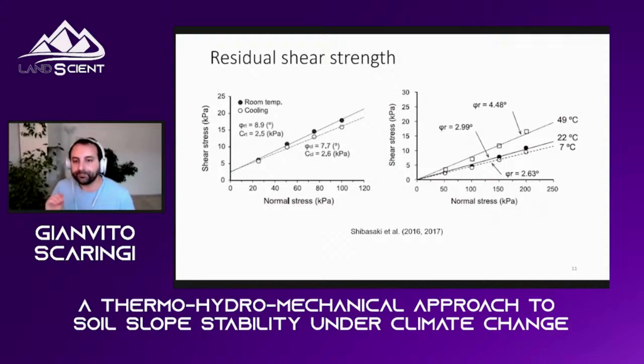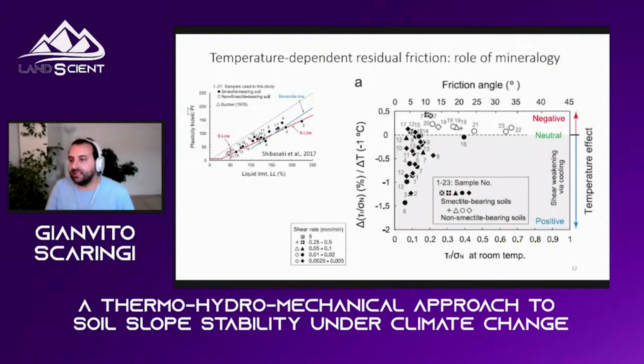However, this thermal sensitivity, which is very large here, depends very much on the type of material that we are testing. It depends on the mineralogy of the clay component, because it's something that concerns the physico-chemical interaction in the microstructure. And in fact, the same scholars analyzed a large number of soils, of clay soils in particular. We see a very wide range of liquid limits and plasticity index in this classification chart. And these are the results that they obtain in terms of effect of temperature on the strength.